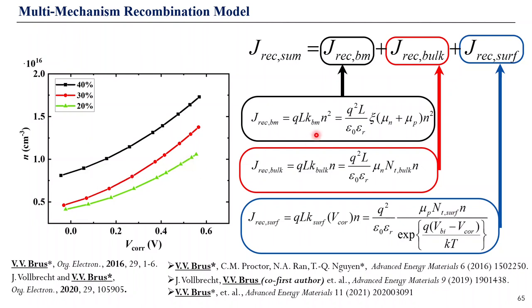And then we need to apply this analytical multi-mechanism recombination model to analyze what's going on in terms of recombination dynamics. So the first equation describes bimolecular recombination in low mobility media, like organic semiconductors. That's the well-known Langevin equation. The second equation describes trap-assisted recombination in the bulk of the active layer of organic solar cells, derived by Professor Paul Blom, who is currently director of the Max Planck Institute for Polymer Research. And the third equation describes the surface recombination at the interface between active layer and electrode for organic solar cells, derived by me. And with that, I completed this multi-mechanism recombination model, which was presented to the organic photovoltaic community and applied to many systems like donor-acceptor bulk heterojunction solar cells.